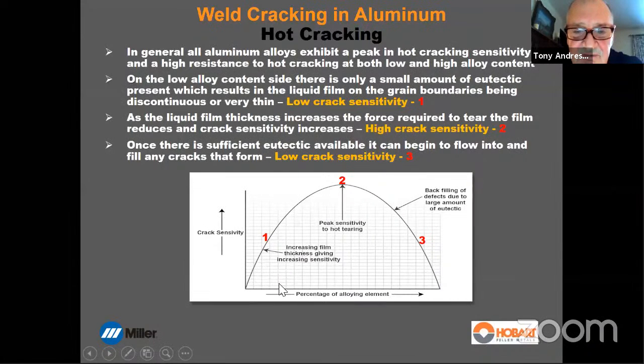And this hot cracking phenomenon has a standard flow, if you like. It starts off very low as we add alloying elements. Very low amounts of any alloying element usually have very low crack sensitivity. Then as we add more and more alloying elements, it increases and increases, and it reaches a peak of crack sensitivity at a certain amount of alloying element. Then as we add more alloying element, it gets lower and lower, okay? So the secret here is to avoid being around the peak of crack sensitivity in terms of alloying element addition. We need to be either on the left or on the right-hand side of the crack sensitivity curve.